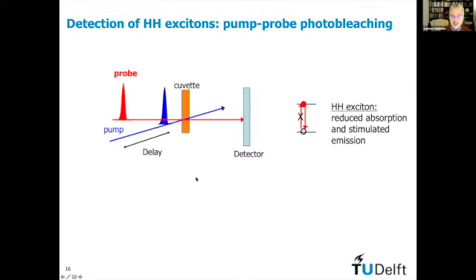Now, to get further insight into what's going on, we also did optical pump and optical probe spectroscopy. So we photoexcite the nanosheets in a cuvette, and then we come in with a probe pulse, which is resonant with the heavy hole exciton. So if you produce an exciton, you get reduced absorption because you have already promoted one electron. There's one electron less to promote, and you can induce stimulated emission of the excited electron back to the hole state. So that gives net bleach. It gives more probe light coming through the sample, and the amount of probe light coming through the sample is proportional to the number of excitons that you have produced with the pump pulse.